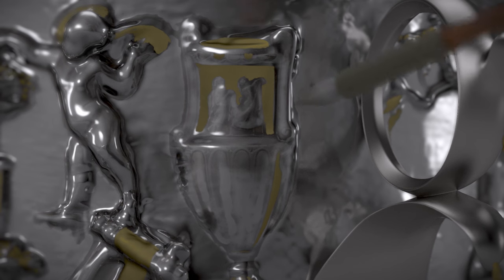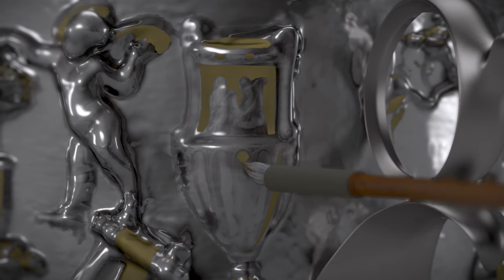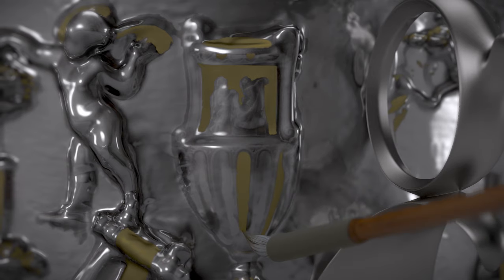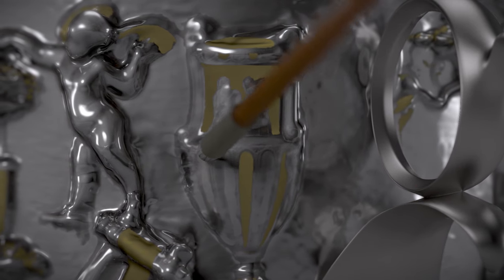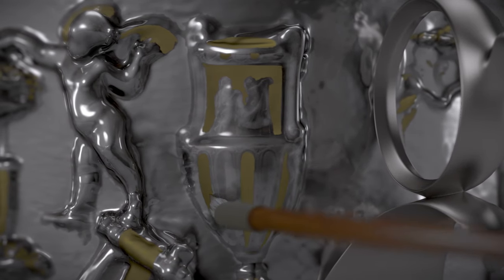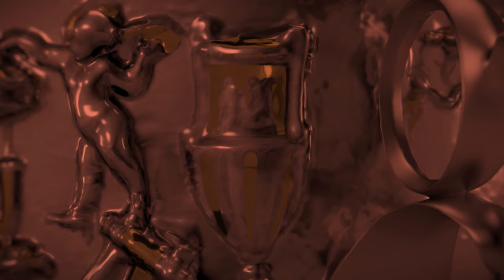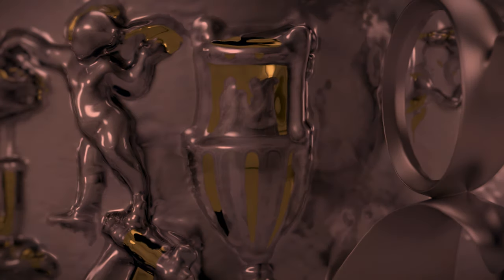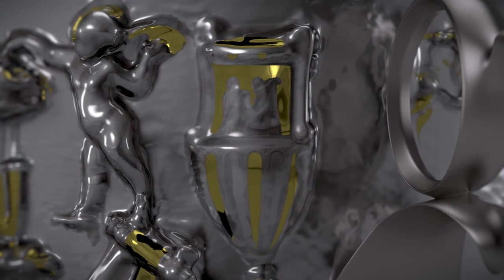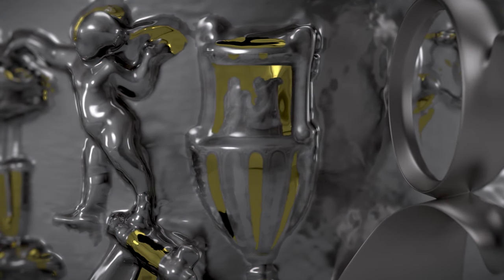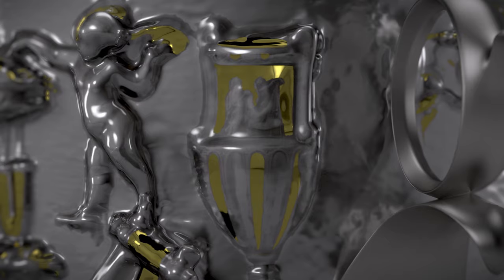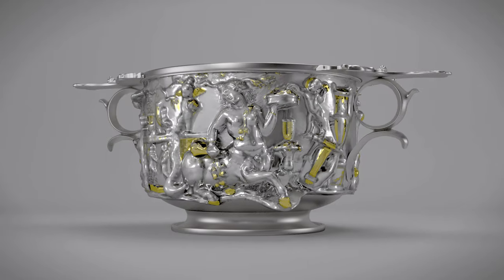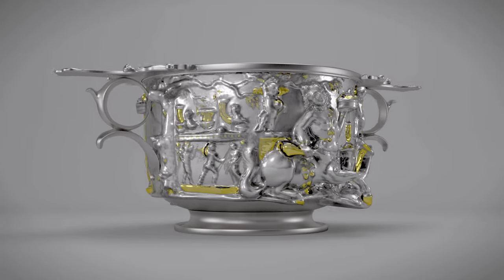Finally, a mixture of powdered gold and liquid mercury, called amalgam, was selectively applied to the silver decoration. Heated, the mercury evaporated, leaving a thin coat of gold over the silver, accentuating elements of the design. The gilt cup was then burnished to a brilliant shine.